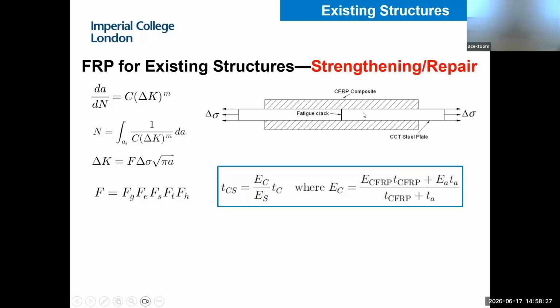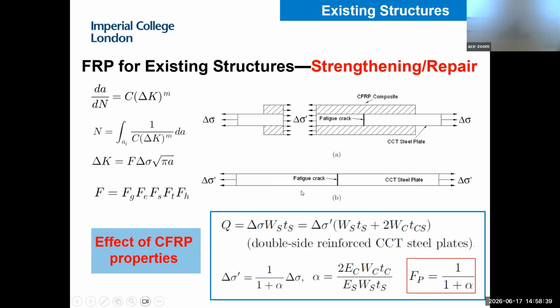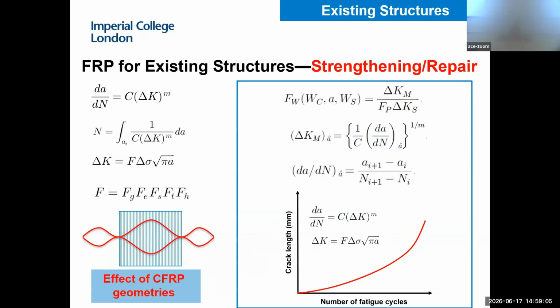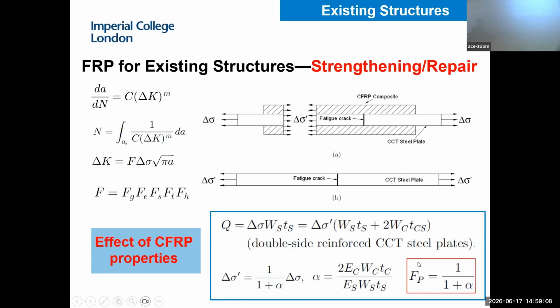So load sharing depends on the stiffness of the two materials. We convert the FRP material into equivalent steel, meaning the steel thickness increases. Then we can calculate the new stress at the crack because of the load sharing mechanism. The new, updated smaller stress is a fraction of the original stress, and that fraction is a modification factor. This modification factor considers the stiffness effect of FRP. So this is the first modification factor we introduced, which considers the material properties of FRP.